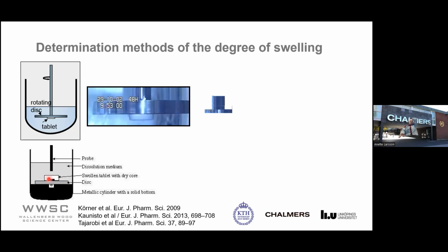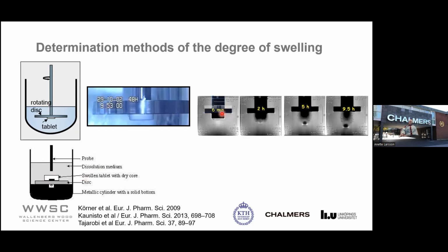Another method is to take the rotating disc, place a tablet on it, and place the whole thing in an MRI, a magnetic resonance imaging function. So here we don't have any gel layer, but here you can start to develop the gel layer, and it goes on, and you create more and more gel layer, and the core is lower and lower. And this technique then opens up for that you can determine not only where you have the core and where the gel layer starts, you can also determine the polymer concentration profiles here.